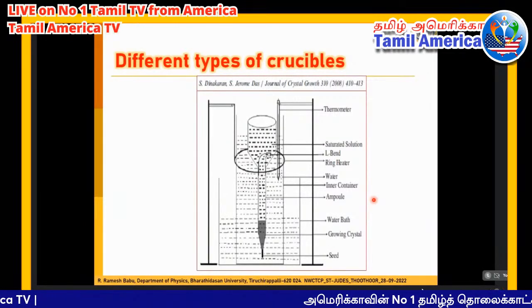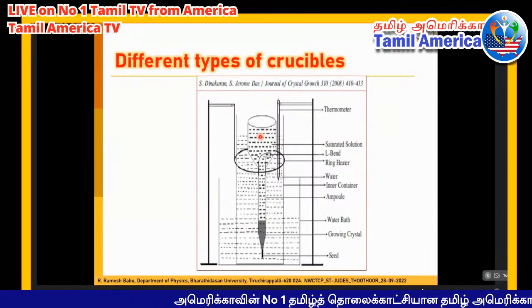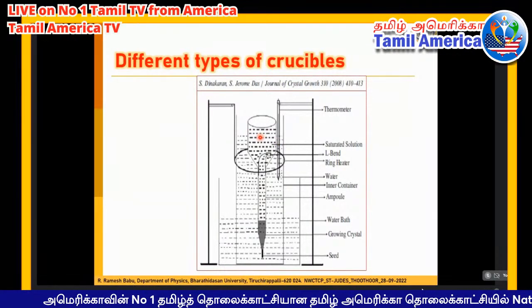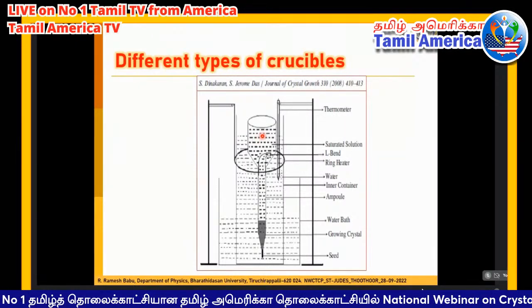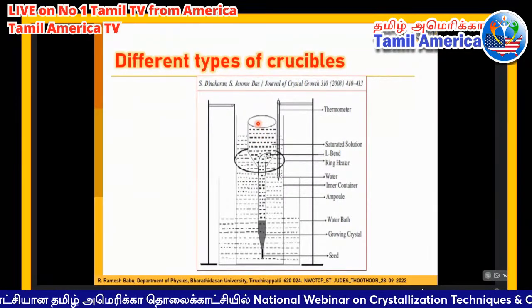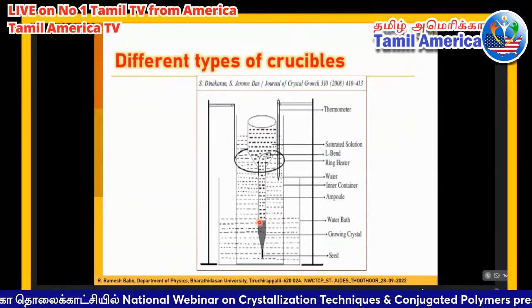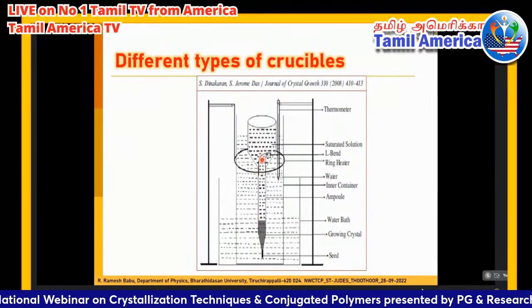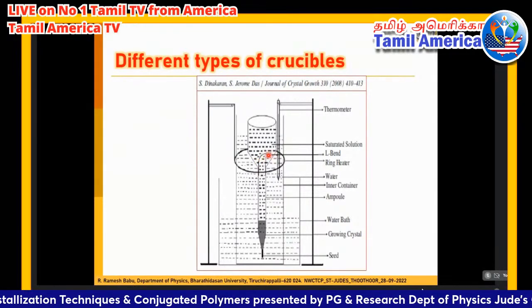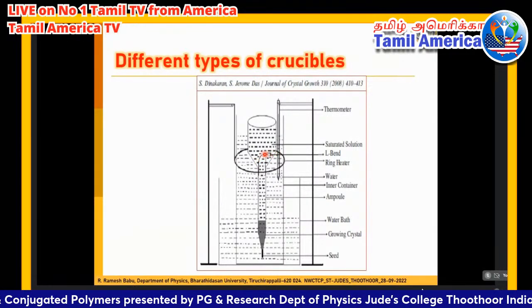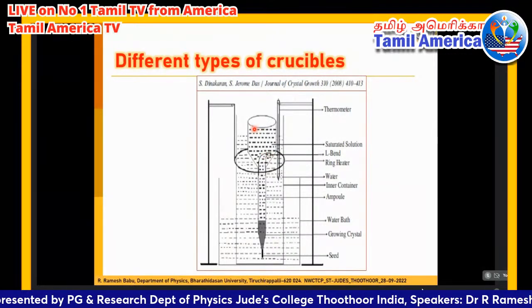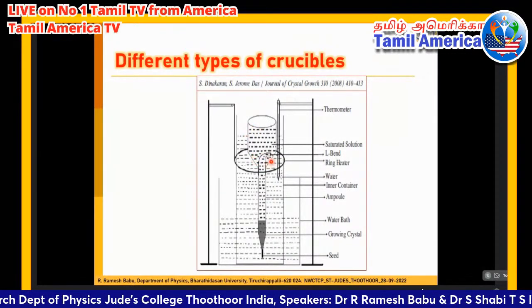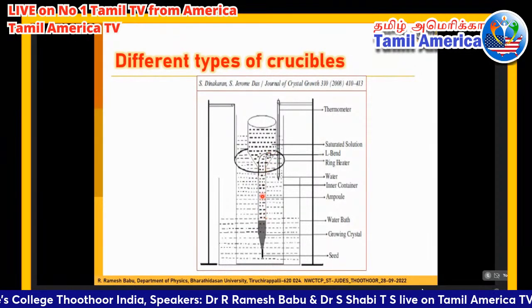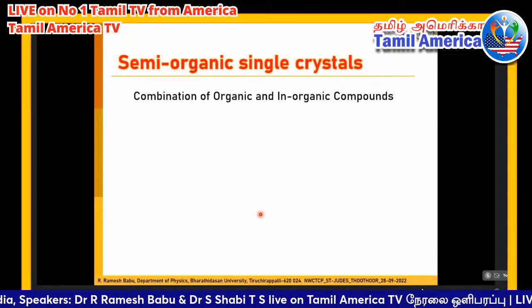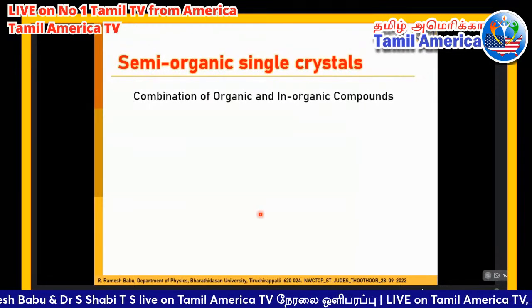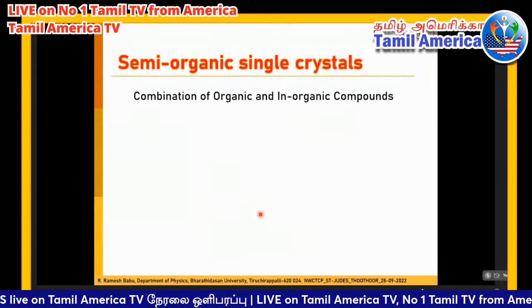And then Dinakaran et al., in order to avoid multinucleations, since usually during crystal growth the multinucleation happens at the top of the vessel and settles on the crystal surface, used bent type crucibles. So at the top, suppose multinucleation happens, that may settle at this side, so then we can grow good quality single crystals. This is one type of modification they made. So far I have given some methodology to grow single crystals, and some basics of applications.